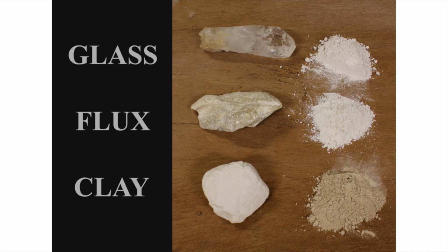Often, the reactions of the silica and flux mixtures cause them to melt uncontrollably and flow off the pot onto the kiln shelf. Now we need to add clay. Clay can control the melt and flow of the glaze, its viscosity. Clay also raises the melting temperature of the silica and flux mixture. Once clay is added to the glass plus flux mixture, it is now a glaze. That is what glaze is in theory: glass plus flux plus clay.